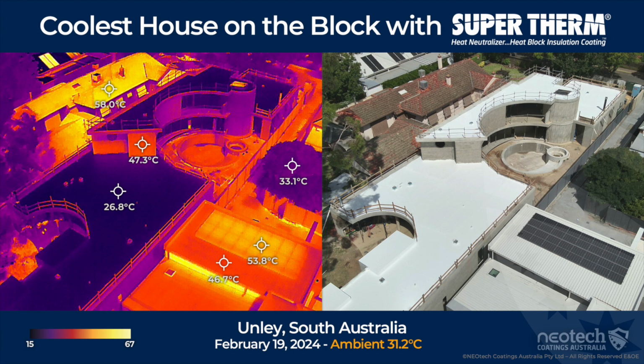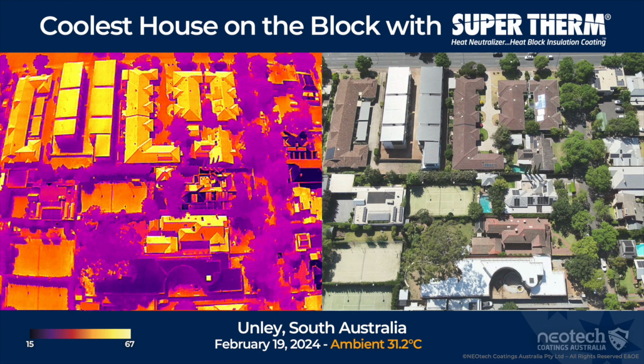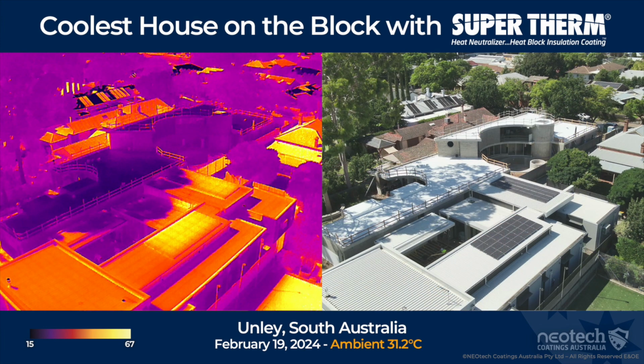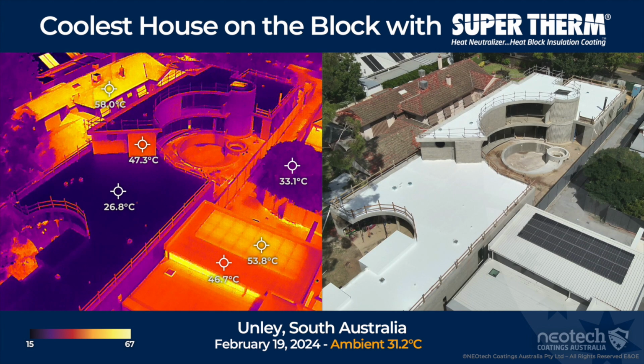This is a fantastic example of when you stop thermal heat load on a mass, a thermal mass, in this case concrete, how the concrete will actually be cooler than both the ambient and the other surfaces around it. So after this house was sprayed, we took infrared readings from there, and you can see very clearly how much cooler the concrete is over the tiled roof next door, the trees even, and clearly the white roof, solar roof down below. So we're talking it was more than 20 degrees hotter on a white roof next door to it. So as far as being cool, now that entire thermal mass of concrete is now stabilised, and it is the coolest concrete in that area. Therefore, it reduces the urban heat island effect.